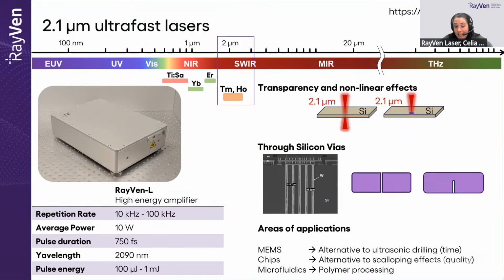And why is 2.1 micron a beautiful wavelength? Simply because of the properties in silicon. At 2.1 micron, 2 micron in general, you're transparent to silicon. So you can go through, nice, but if you focus down, you actually trigger a nonlinear effect, I meant filamentation, with very little energy per pulse. And you can thus process directly inside the volume of the silicon.